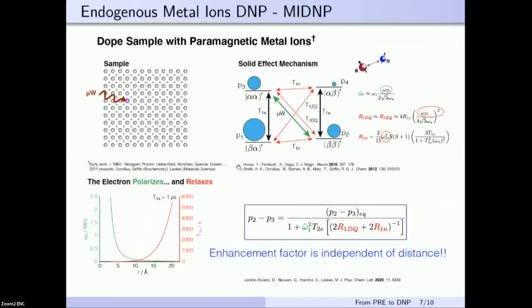the DNP enhancement is independent of the strength of the dipolar coupling. So whether it's weaker because it's farther away, or because it's at an angle to the magnetic field that is not favorable, it doesn't really matter. I think the enhancement is going to be homogeneous throughout the sample, and this is what we observe. We see no changes in the line shape from microwave on to microwave off. So we see changes versus build-up time, because first we build up the magnetization of nuclei that are closer, which are broader, but this happens in both cases, with enhancement and without.